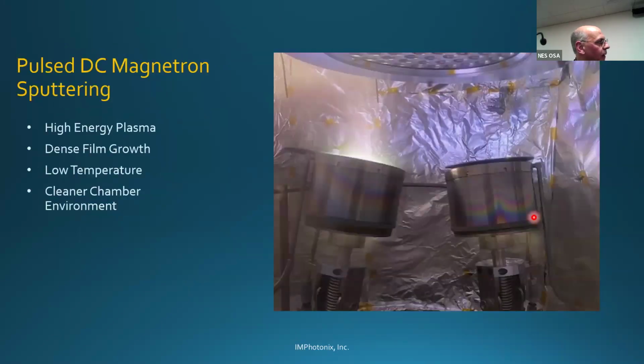And I can't leave out sputtering, which is a whole different type of evaporation. Rather than relying on the energy of the molecule as it evaporates, leaving the gun, you're creating an electric field, a plasma, between the source and the substrate, which helps you have better stoichiometric uniformity of the material. With physical vapor deposition, you have to be very careful how you control the deposition, because if you don't do it right, you get inhomogeneous films. May start out at one index and end up at another index. With sputtering, it's much more reliable. What you start with, if you're doing a thick film, ends up with the exact same stoichiometric parameters.